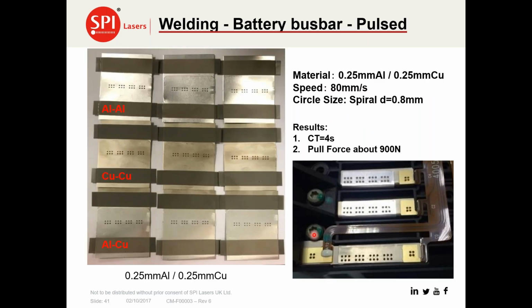Again, this is a more specific application of pouch type cell applications where the tabs are bent over, and here you can see an array of, I think it's 24 spot welds that have been done in 4 seconds. And again, this is an actual application. And in terms of the development process, we're looking at aluminium to aluminium, copper to copper, and aluminium to copper.